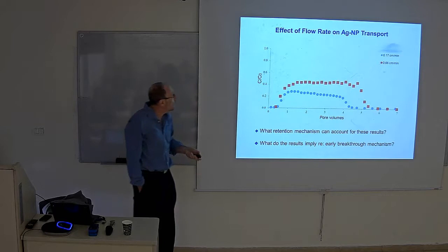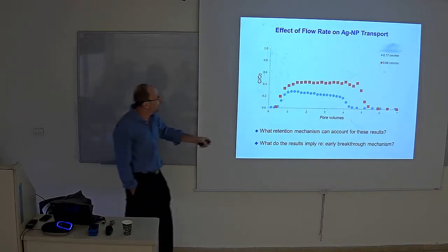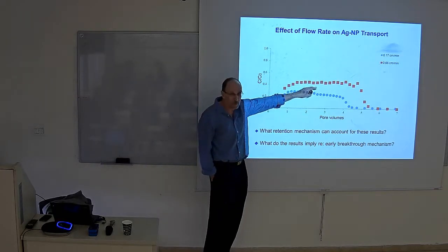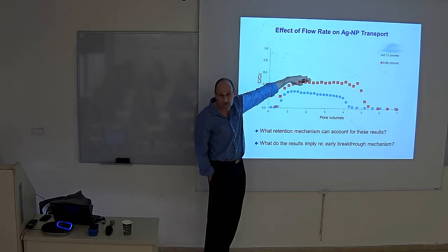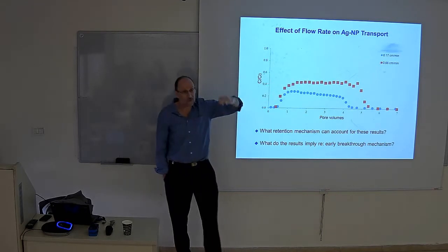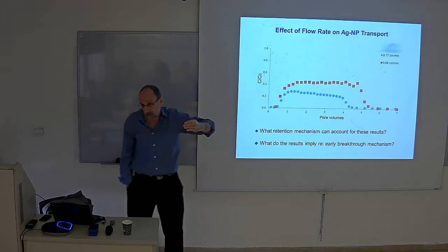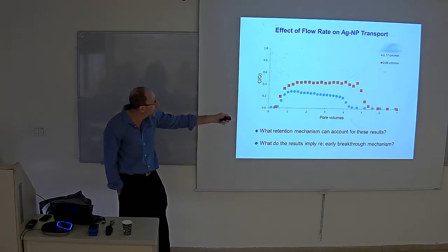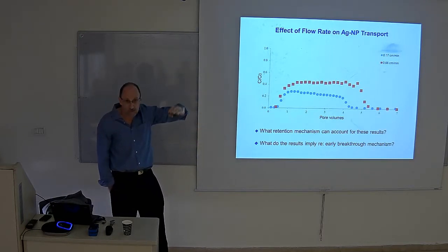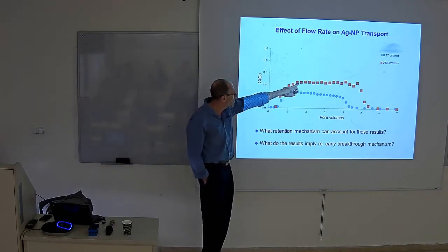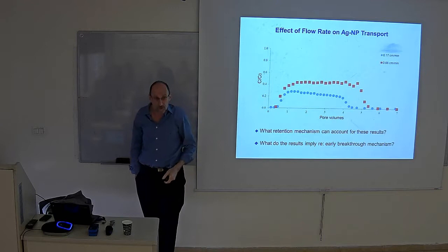And then we say, okay, now let's look at the effect of the flow rate. As you might expect, higher flow rate, you get more material breaking through. Why? Because there's less time for sedimentation. That makes sense, right? A slow flow rate, the blue there is a much slower flow rate, so some of the nanoparticles can settle out, they're moving faster, but still you only get 40-45% recovery.